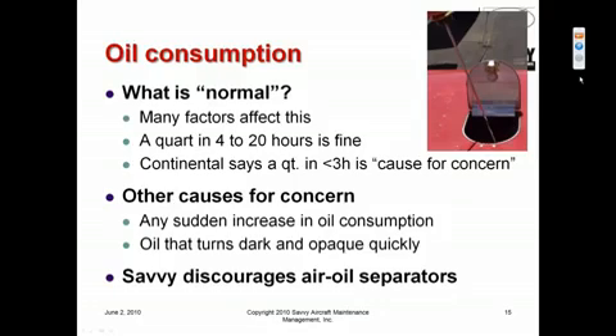On the other hand, a sudden increase in oil consumption due to greatly increased blow-by can indicate something that's fairly serious, like a broken compression ring or something like that, or an overheated and annealed compression ring. So we want to do some investigation to figure out what is causing the increase in oil consumption, so that we can determine whether it's serious or not.